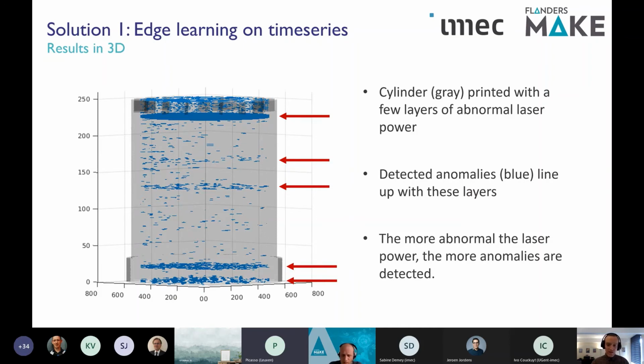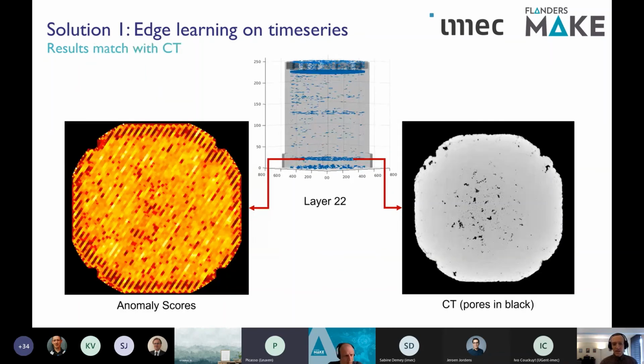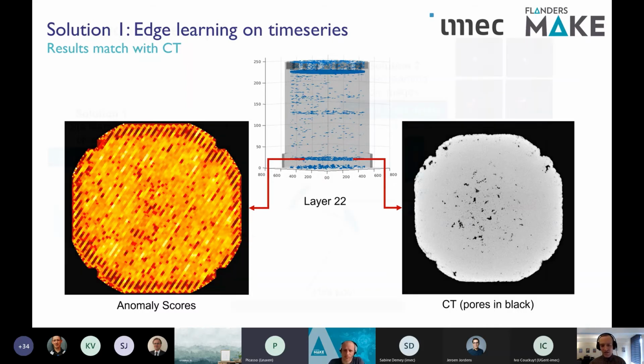Now, if we zoom in on a specific layer on the next slide, so we got a layer near the bottom here, we can see that the anomaly scores that we compute are rather high, and that's shown by the yellow and orange that we see in the image on the left here. Now, if we compare that same slice in the object to a CT slice of the same object, what we see are a lot of pores or voids in the object that was printed, and these are showing up in black here on the right. And so these are the types of defects we want to avoid. And so the fact that we're seeing the anomaly scores correlating with those defects gives us a decent indication that this type of approach would be helpful for online control. So with that being said, I'll hand it back to Dries for the other system.